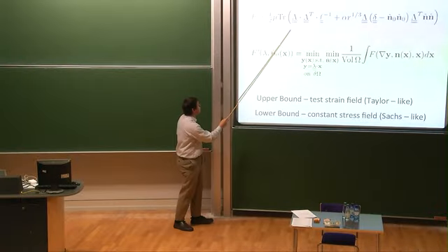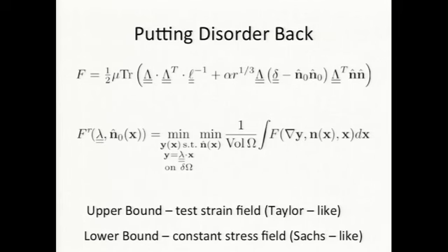So this part we saw actually was completely degenerate. It didn't care whether it was perfectly aligned or in the complicated domain structure. This part hopefully is going to incentivize the complicated domain structure, so it explains why we don't see any spontaneous state change when we just cool it, and we do have to do a little bit of work to stretch it out.